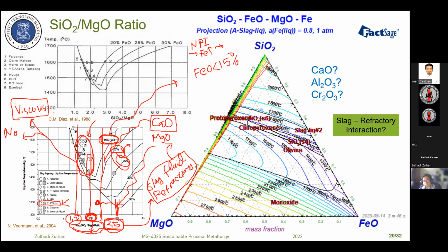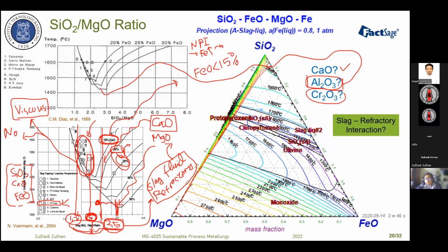This figure is actually what people believe until today. They just consider SiO2, then MgO, and the last one is iron oxide. Now we think that besides these main components in the slag, there is also a small amount of alumina, but alumina could be high, and chromites in between CaO and alumina. So the presence of alumina in the slag should be considered, and this diagram should be revised. It's actually not only SiO2, MgO and iron oxide; the presence of alumina in the slag should also be considered.